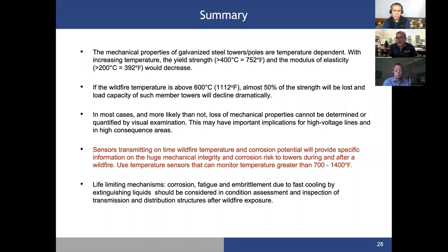In most cases, just looking at these structures cannot determine the change and quantify the risk that they are under. This is very important: knowing the temperature, you should do direct assessment. There are sensors available that transmit the wildfire temperature and corrosion potential immediately during and after exposure to wildfires. These sensors could be very important in identifying specific structures that need special attention and condition assessment.